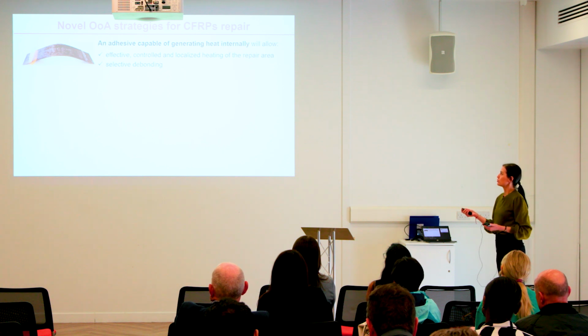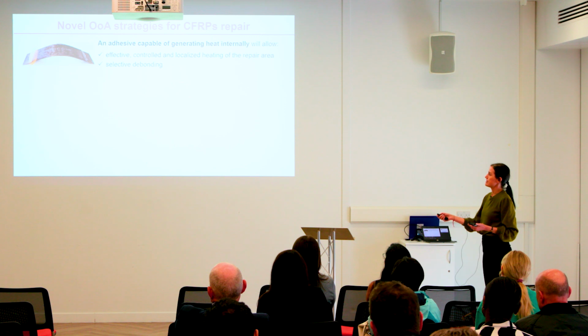Because this will allow an effective, controlled, and localized heating of the repaired area. So basically, we will be applying heat only in the interesting part, in the bonding area, without heating anything else. And it will also allow a selective debonding. More specifically, electrically conductive epoxy nanocomposites emerge as very good candidates because they offer very good Joule heating properties, as we are going to see afterwards. But basically, once we are above the percolation threshold, when we have an electrically conductive nanocomposite, it has the ability to transform an electric current into heat, generating heat from inside, internally, as we are going to see afterwards in more detail. And in addition, only a nanostructured electrical component will actually fit within the bonding lines, whose required thickness is normally in the range of a few hundreds of microns.